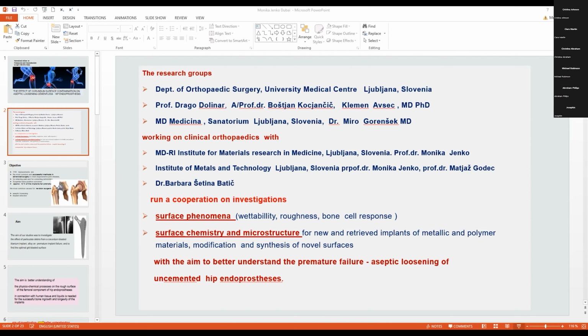Methods where multivariate analytical methods were used: contact angle, water measurement, and profilometry for hydrophilicity, wetting properties, and roughness. This is a Licona device. Then we use scanning electron microscopy, a field emission scanning electron microscope, Zeiss Gemini Crossbeam 550, with integrated techniques like energy dispersive X-ray spectroscopy and electron backscatter diffraction to examine surface, chemical composition, morphology, phase analysis, and of course, microstructure.